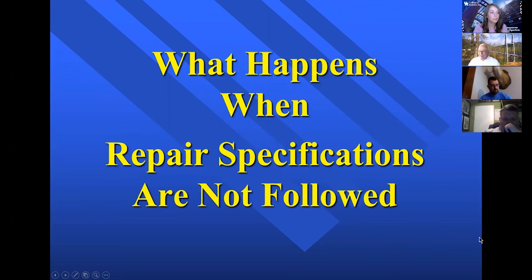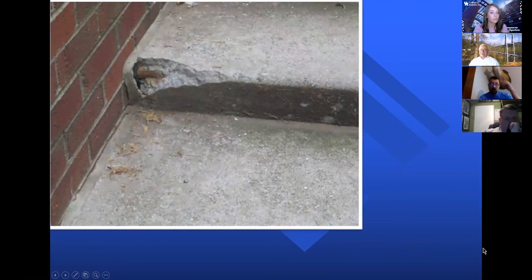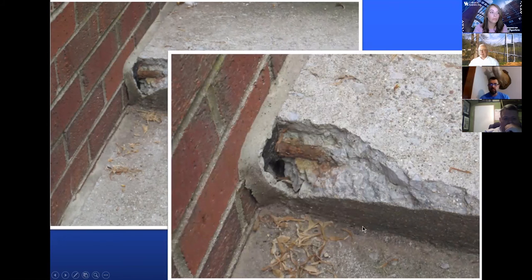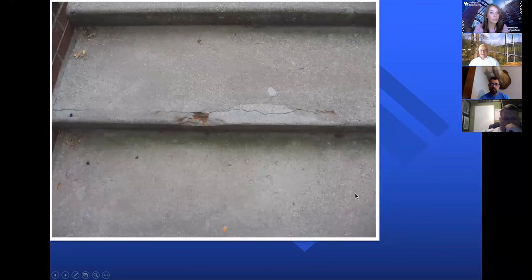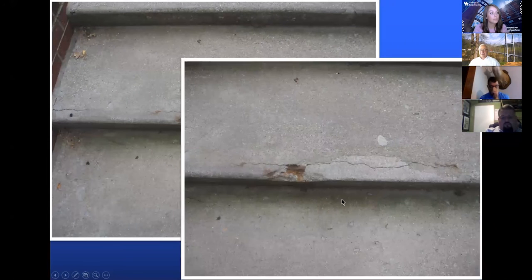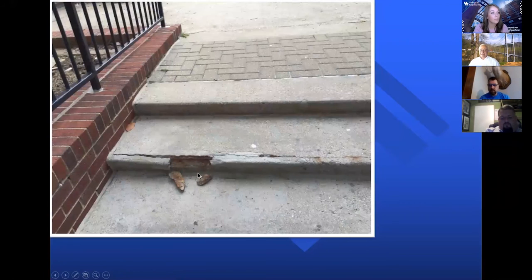So whenever we do a design for the repair, we have construction specifications or repair specifications. This is on UK's campus, and there's tons of them. A lot of the steps you see rusted rebars and concrete spalling. And I mean, this is very typical, not only on our campus, in many other areas. But look at this, these steps. These were already repaired with some of the best concrete you could buy at Lowe's. But what they failed to do, they failed to remove the bad concrete and clean the rebars. So after a while, that repair also failed.